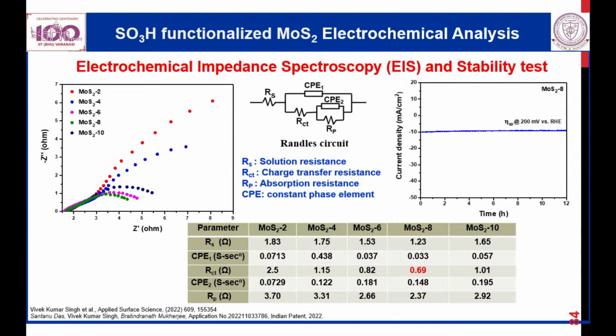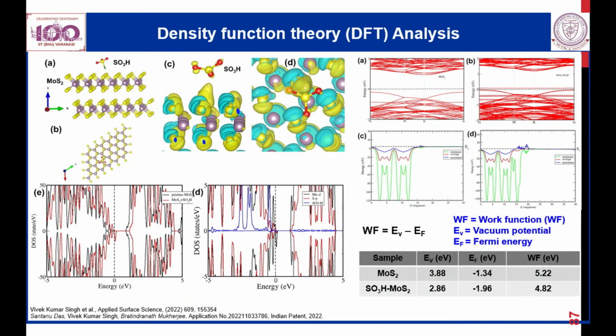These are basically the supplementary data in support of our claim of stability of the material, which is almost 12 hours of stable current. We have some impedance results showing the charge transfer resistance and kinetics. And the most important part that we have focused on is developing the theoretical understanding. If sulfonated material goes to a site and populates over the surface of MoS2, you see the sulfonated molecule populated on a layer of MoS2. So basically they created additional density of states. You see the additional blue colored sulfonated density of states.